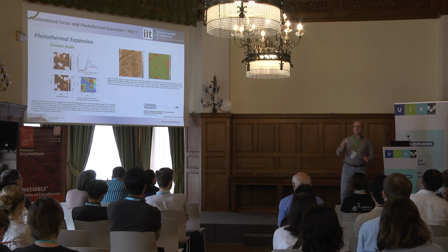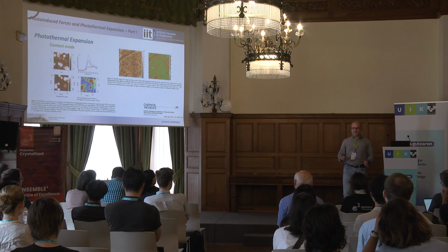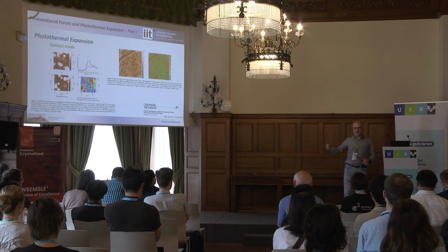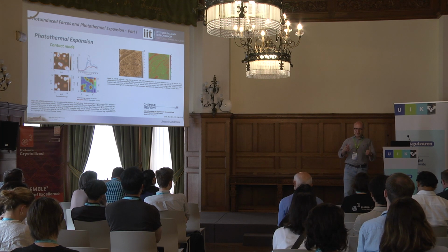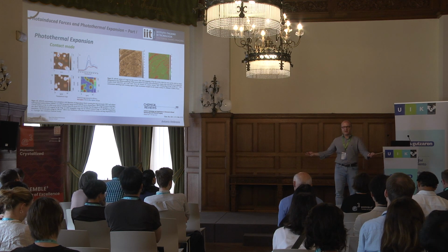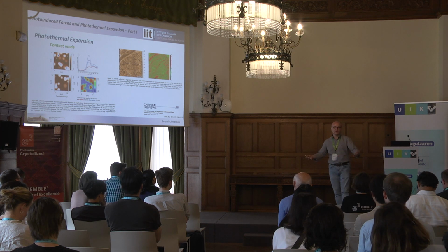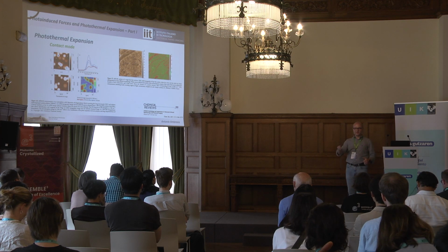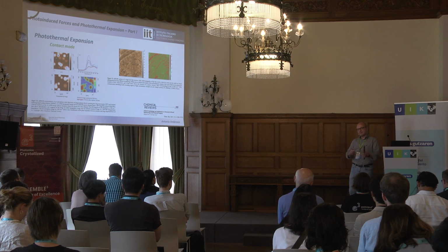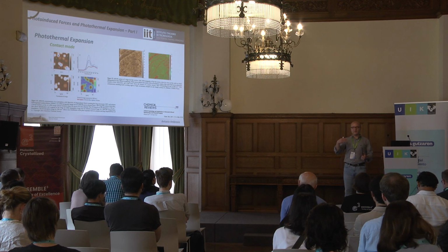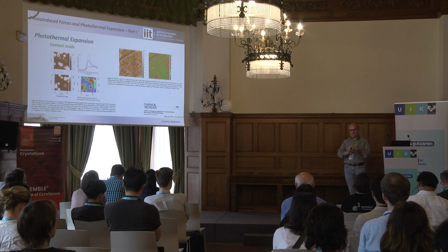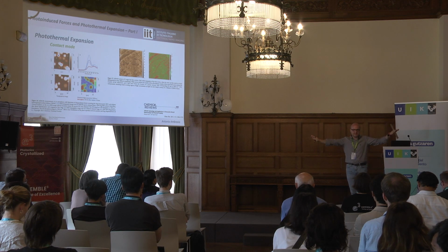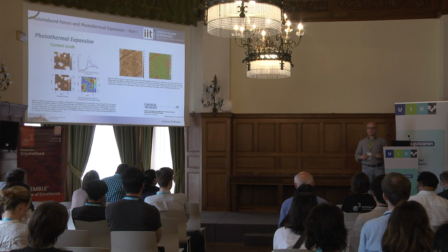Again, not always, right? It depends pretty much on the material. And this is something that I come back to later, because you need a material that is keen to expand in the direction that you are probing, and also have a limited diffusion. Otherwise, whatever excitation you do like that will wash out, right? That's basically what you are saying, right? And that also doesn't give you a resolution, but before resolution, it does not give you signal in that sense, right? Because it's not expanding in this direction, it's basically spreading away. Yeah. Thanks.